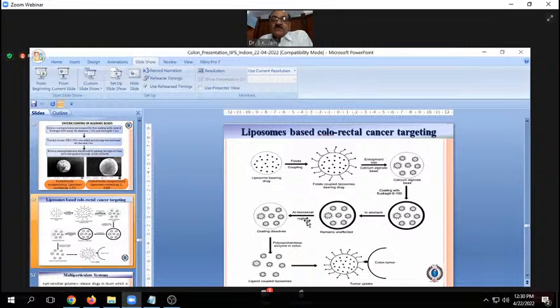But when it reaches the ileocecal region where pH is greater than 6.5, the enteric coating will dissolve, right? And by the time the coating is dissolved, the calcium alginate will reach the colon. In the colon, polysaccharide enzyme will digest the calcium alginate, right? And release the surface modified liposomes. And since the surface of the liposomes is modified by folic acid, and the receptors of folic acid are overexpressed on the colonic tumor, right?